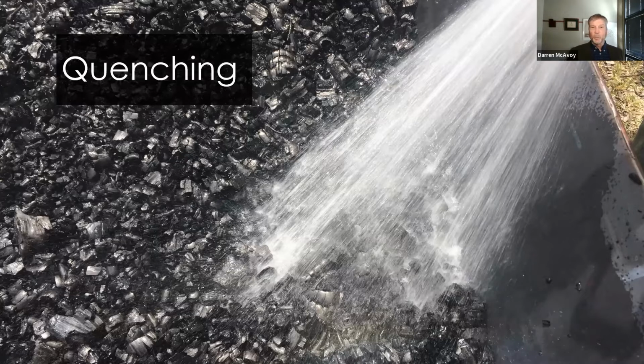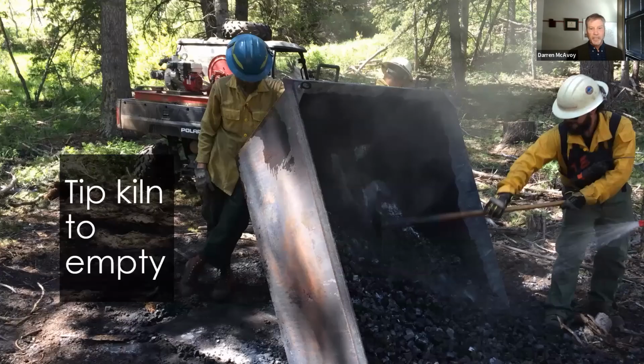A critical part of the process is quenching, so it does require water for this. It is possible to dry quench, but it takes a lot more work, and I'm not going to talk a lot about that, but that is possible. I tend to use water, bring in a tanker, an engine or something, sometimes pumped straight out of a creek, and quench the kiln. These smaller kilns take about 70 gallons of water to quench. And you can see that's washing a lot of the ash off.